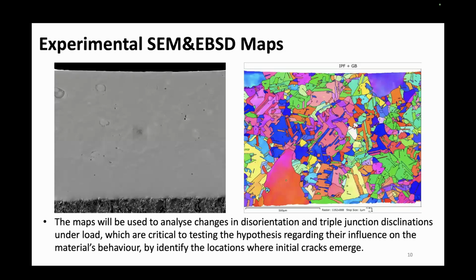I don't know why it's not showing, but this is our preliminary analysis of the test, which should show the grain change and grain orientation change during the test. And this map will help us analyze the change in disorientation and triple line disclination, which are critical for us to test our hypothesis regarding the influence of triple line material behavior, especially by disorientation or by triple line disclination, and we can identify the location where the crack initiates.